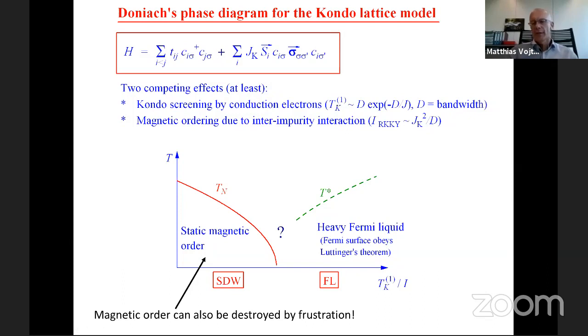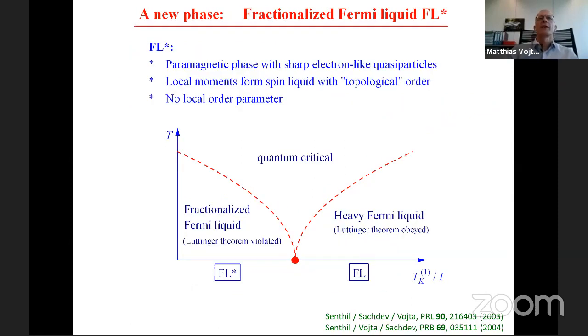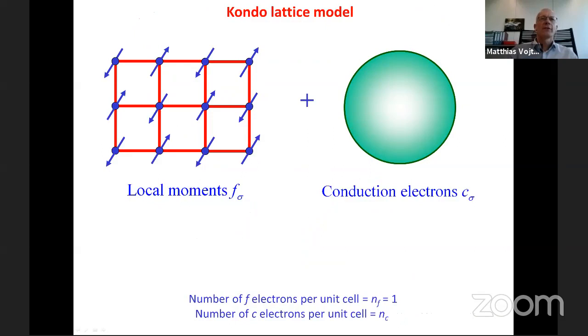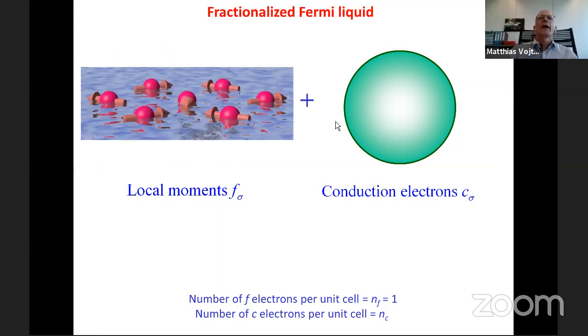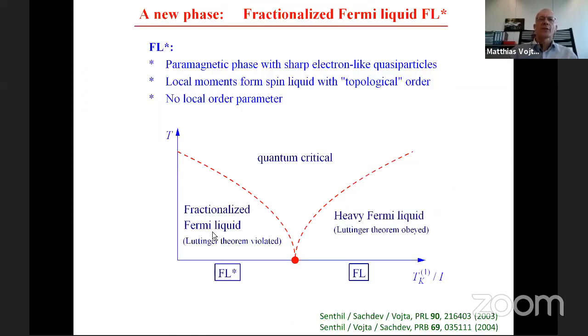And that is a situation which we considered a few years back. We came up with a modified phase diagram here, which now applies to a situation in the presence of strong frustration. We now look at this Kondo lattice system. The phase diagram has the same axes as before. There's a heavy Fermi liquid on the right-hand side. But now we have a new phase here, which we call a fractionalized Fermi liquid. What is this? This is, symbolically speaking, a situation where these local moments form a spin liquid. And this spin liquid happily coexists with the conduction electrons, and the two subsystems interact only weakly. This is a fractionalized Fermi liquid.